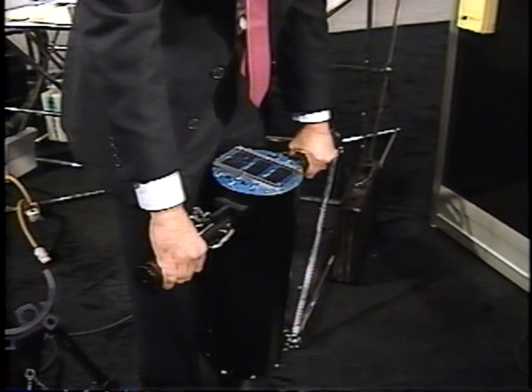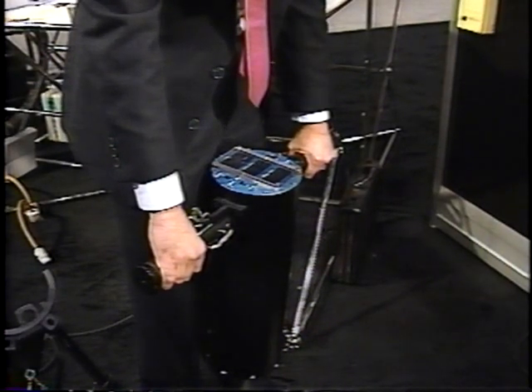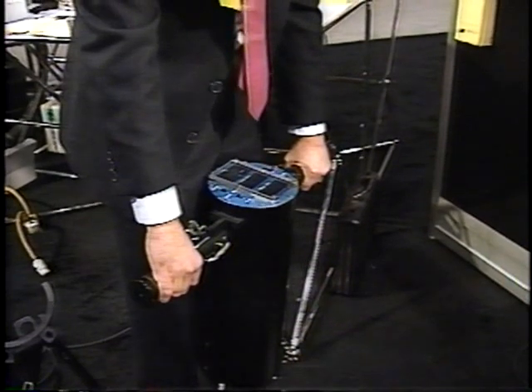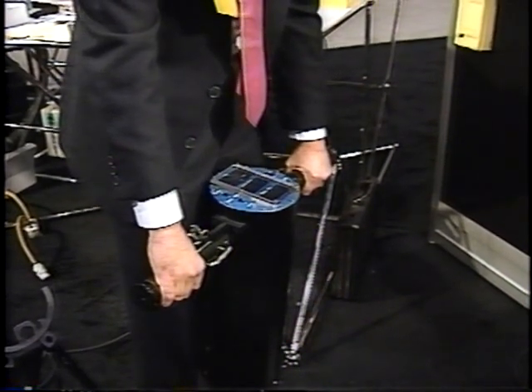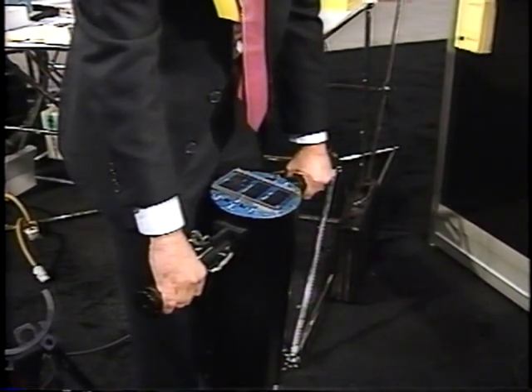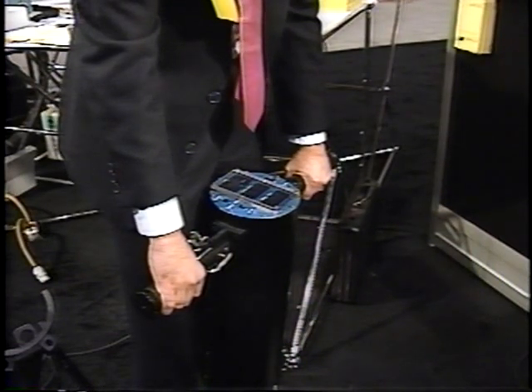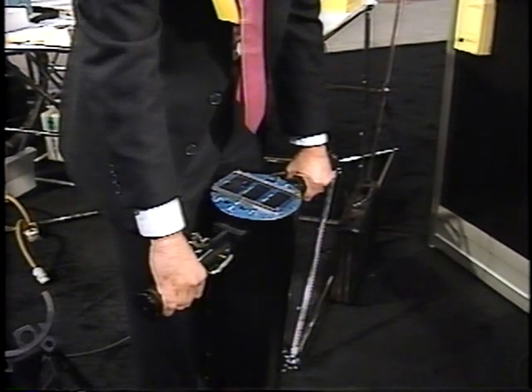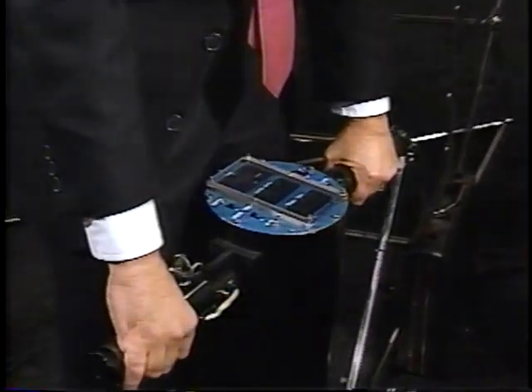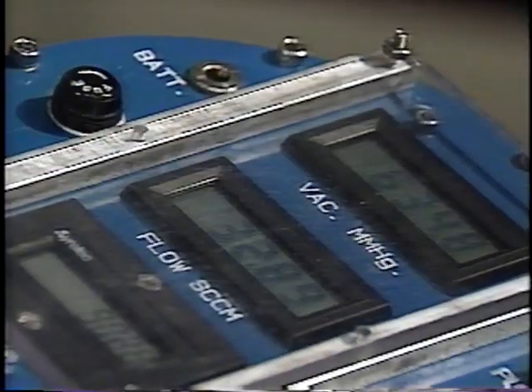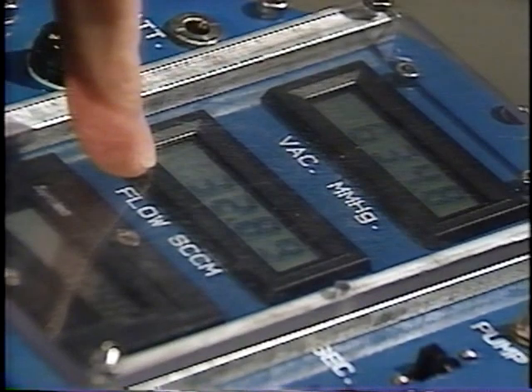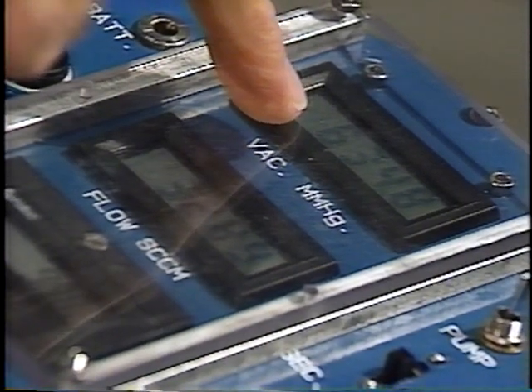Our permeability scale runs from 0, which would be essentially impermeable, up to the capacity of the meter, approximately 100 cubic centimeters per minute. This concrete reads 30 cubic centimeters per minute, which is a very high value. This shows the flow reading in cubic centimeters per minute, and this is the vacuum level. We operate at a vacuum of about 620 to 640 millimeters of mercury.